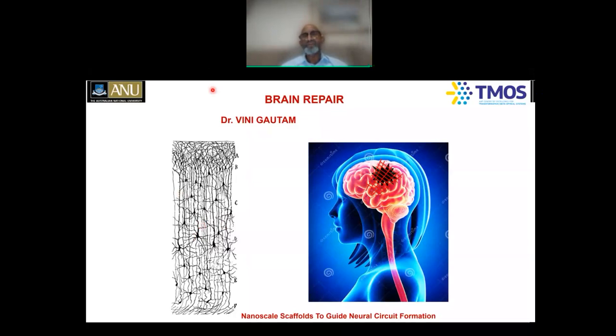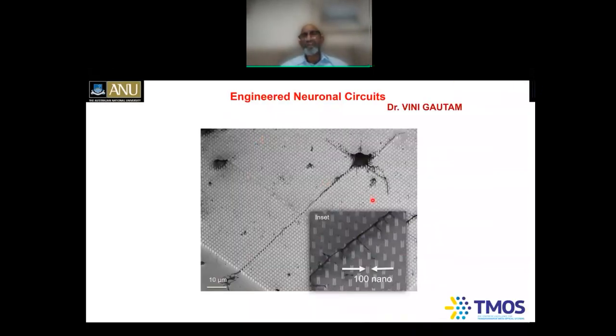Vini Gautam. She was in my group earlier, but now she's a lecturer in biomedical engineering at the University of Melbourne. So Vinnie has spent about 2 years optimizing various conditions and protocols to grow these neuronal cells on top of these indium phosphide nanowires. You can see the uniform distribution of these indium phosphide nanowires, and these axons or neurites really like to follow these patterns beautifully here. You can see the dendrites which are coming out and following these patterns as well.